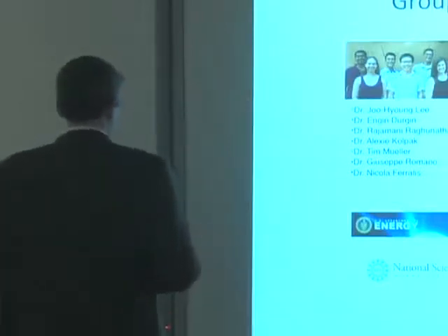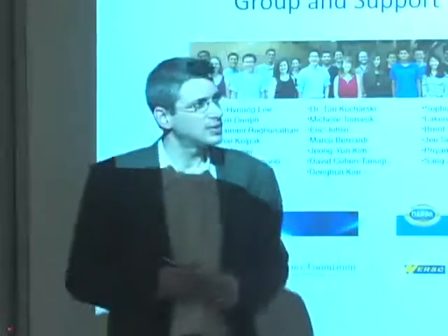I was wondering, for the all carbon solar cell. Great question. We are doing high-res TEM, trying to understand what is where. We're doing calculations, as I showed, between these different interfaces, including now RGO, which is in itself a highly complex and rich material. Right now we don't know whether it's an electronic effect, helping to get the charges out and separated, or whether it's simply a morphological effect. The RGO may be helping to phase segregate, helping you reduce bundling of the nanotubes, which is always a problem. Hopefully in the next month or so, we might have answers to that question.